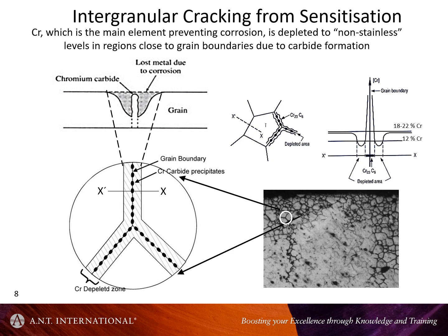And in principle, what happens is that if you have a grain boundary and you deplete the chromium in the region close to the boundary, either because of carbide precipitation or by some other means, then you can reduce the chromium level to below the level at which it would be an effective oxidation retardant, and you can get either dissolution or oxidation of the material in this volume.